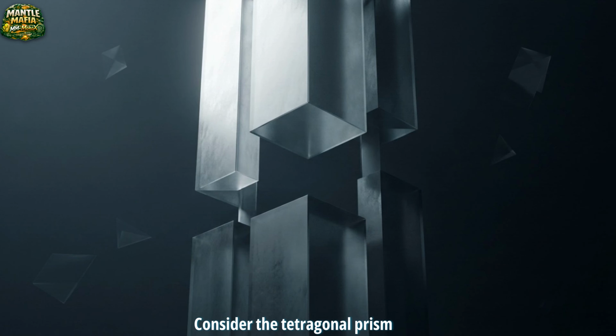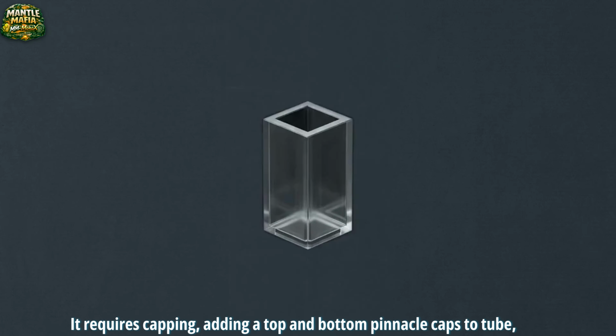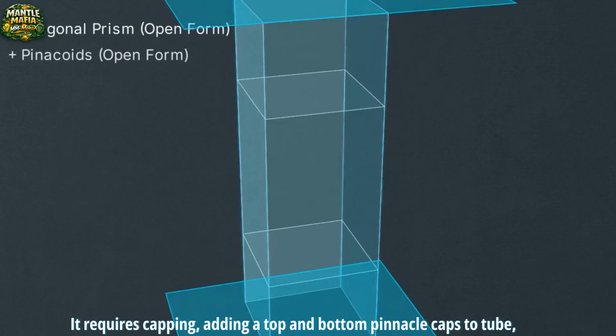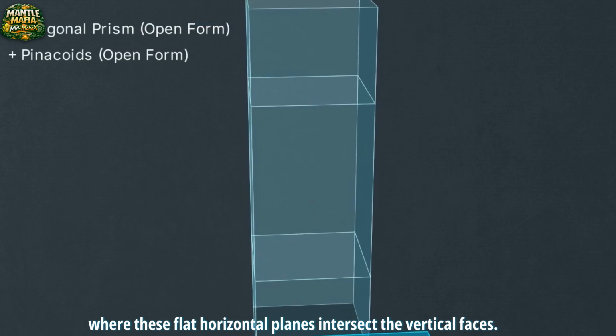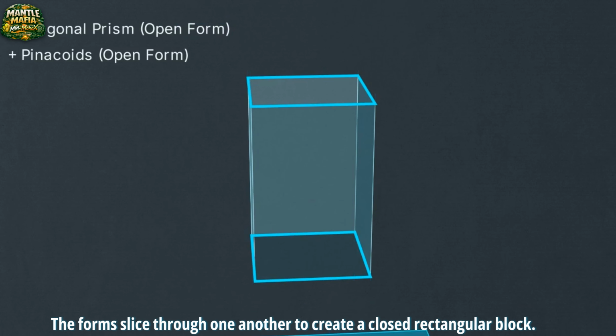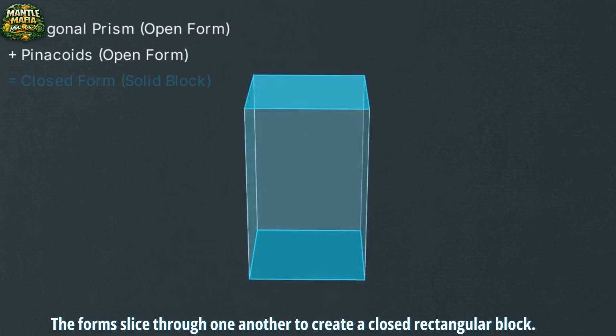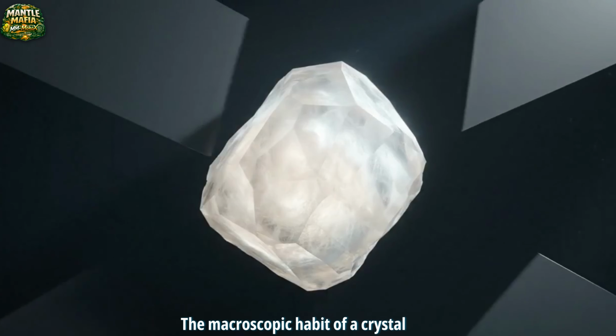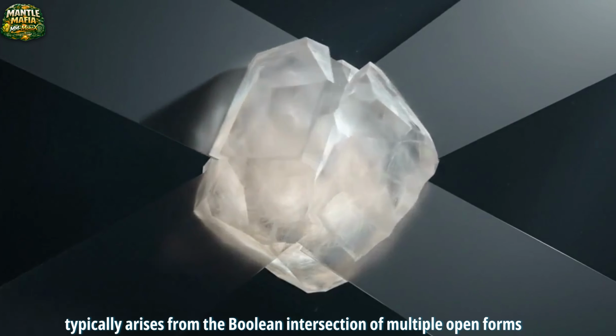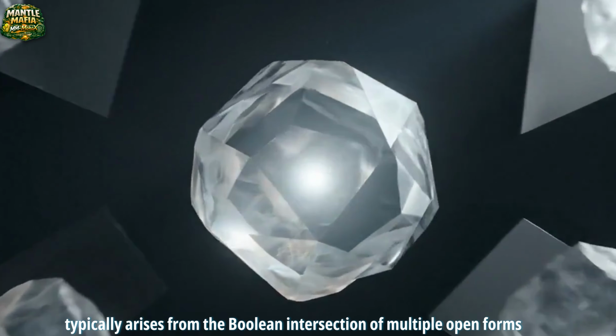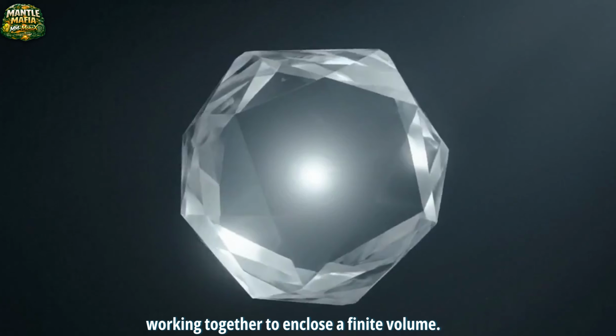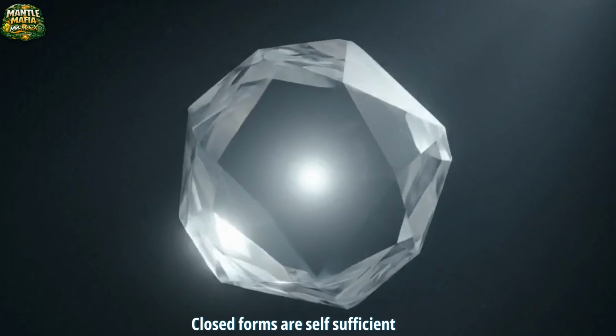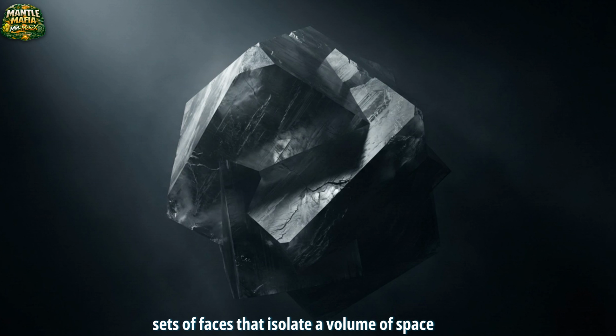Consider the tetragonal prism. As an infinite, 4-sided open tube, it requires capping. Adding a top and bottom pinacoid caps the tube. Where these flat horizontal planes intersect the vertical faces, the forms slice through one another to create a closed rectangular block. The macroscopic habit of a crystal typically arises from the Boolean intersection of multiple open forms, working together to enclose a finite volume.